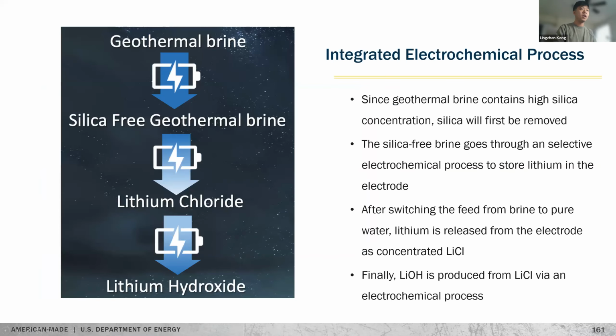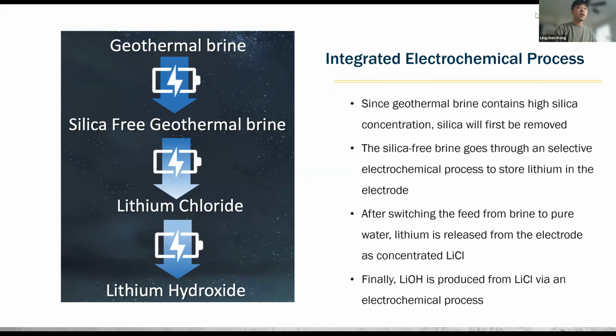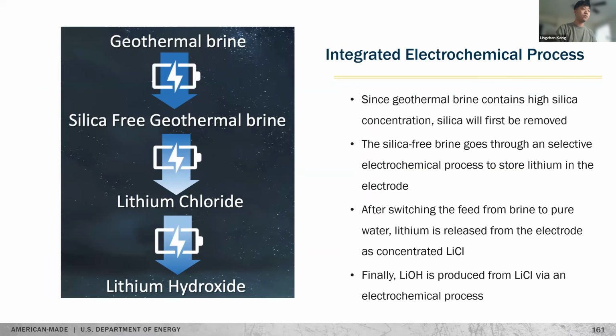Next slide, please. This is just the same description of how the electrochemical process works. We propose an integrated electrochemical process with a total of 3 steps, because we know that geothermal brine contains a very high silica concentration. So we propose to remove silica first from the brine with an electrochemical method. And then the silica-free geothermal brine will go through another electrochemical process, which is the selective lithium extraction with a lithium selective electrode. And the next step is we utilize another electrochemical process to generate lithium hydroxide from lithium chloride.